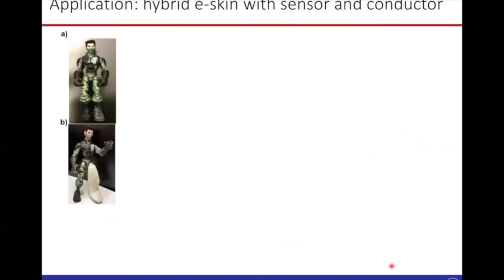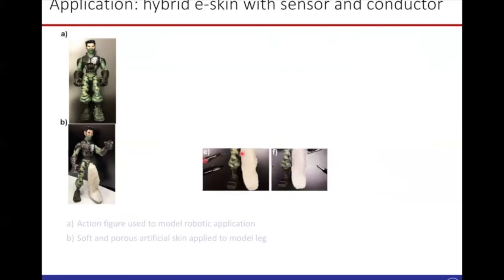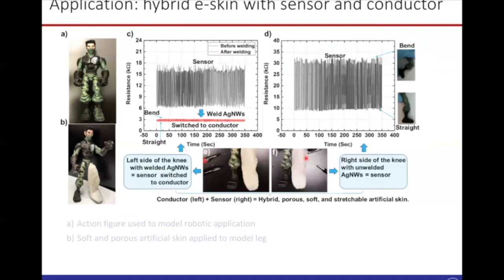Now we prove the application of this concept to develop a hybrid e-skin for an action figure. Here we show an action figure with and without applying a skin on the right leg. So first we develop a skin on the right leg. You can see here. Then we develop two silver nanowire networks, one on the left side and one on the right one. We perform a bending test on this leg, meaning that it takes two positions, straight and bent. While you bend, the skin here will stretch and the resistance of the network changes. As you can see, a large change in resistance on the right skin, right network, meaning that it can behave more like a sensor.